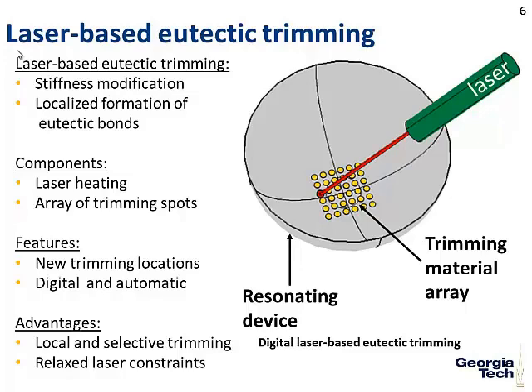Finally, because we have a laser, we can have a digital and automatic process. I'll go into more details. Also, compared to, for example, mass ablation, our laser has far fewer constraints. We don't need it to be as large, because what's really important is not the size of the laser. What's important is the size of the gold spot that is diffusing into the silicon and creating those eutectic bonds. So if a laser beam is bigger than the gold, it's okay, because what matters is the size of the gold spot that's diffusing in.